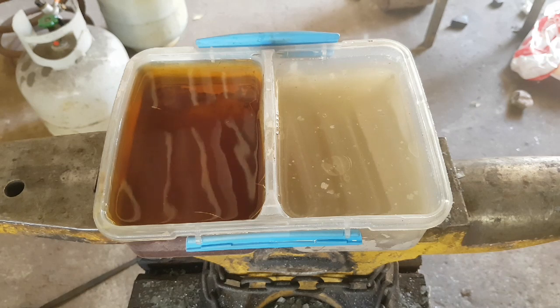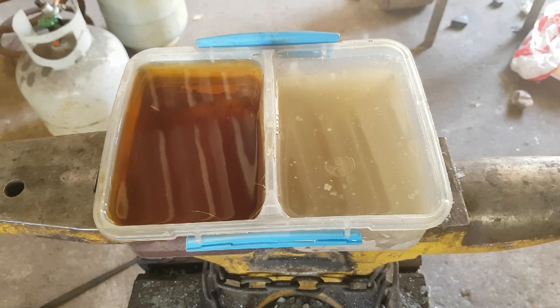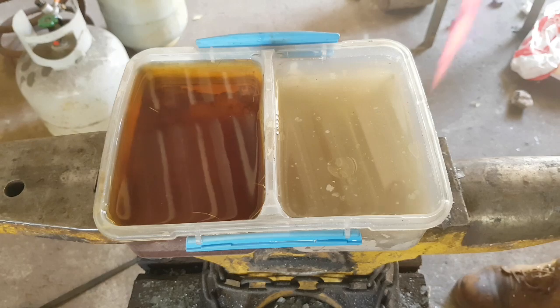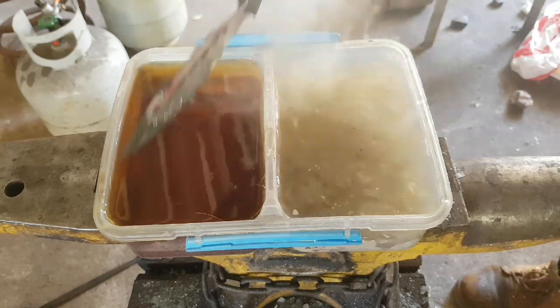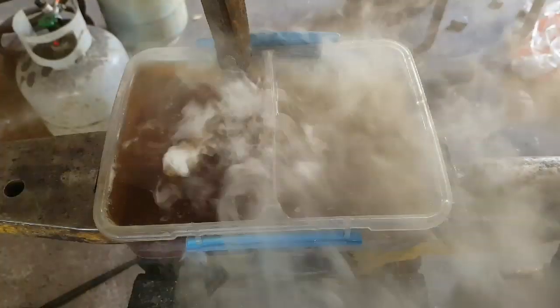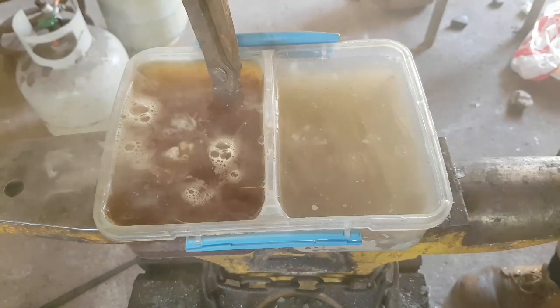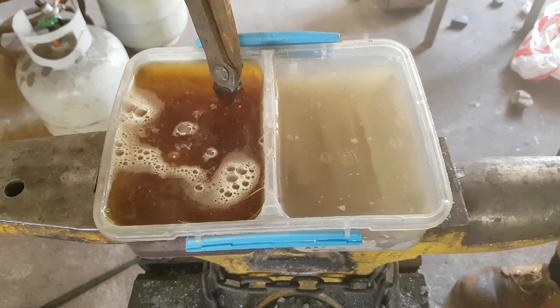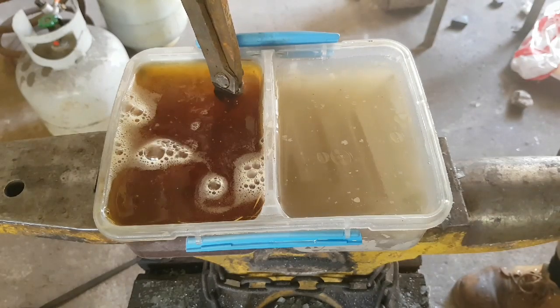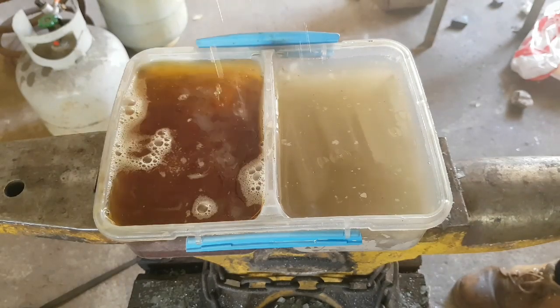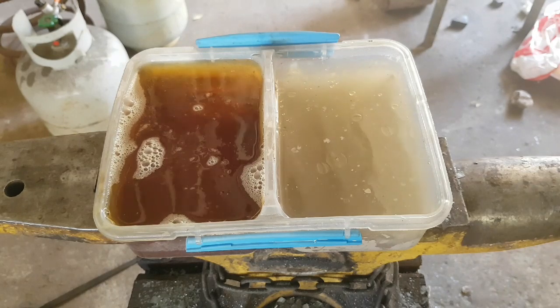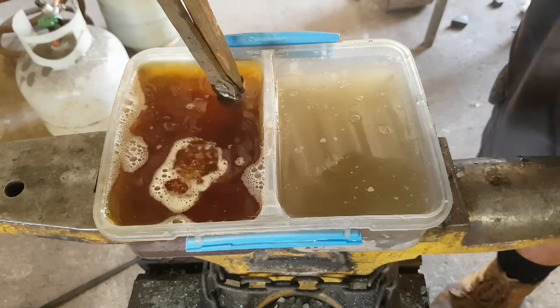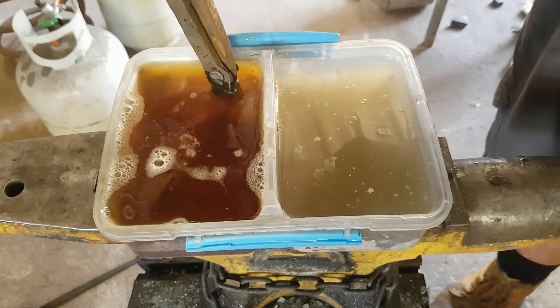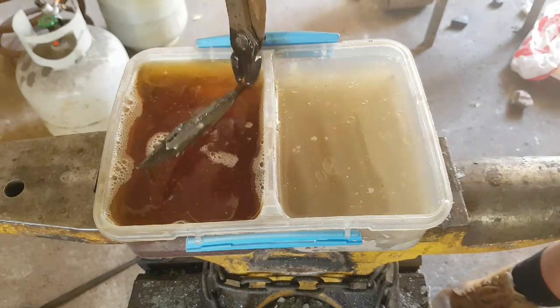And here we go, we're going for an interrupted water quench. So you'll notice that I come out of the forge, straight into the water, and then after about 2 seconds, straight into the oil to slow that cooling down. This means that I'm less likely to crack the blade, and luckily I didn't crack this blade. But you will notice that as I quenched in the water, the Satanite shrunk back and started to crack off from the blade, and that's totally normal. That doesn't mean that you won't get a Hamon.